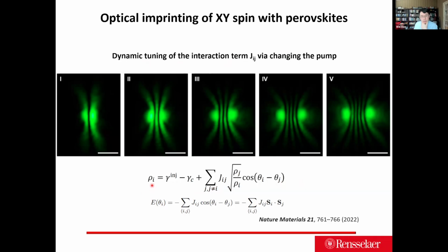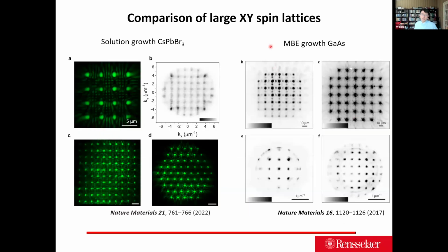So each spot density follows a relationship like that. So essentially one can map the system into a spin Hamiltonian the same way as the gallium arsenide system. So we can nicely, directly optically read the spin configuration in the two condensate case. And interestingly, we also want to compare the simulation in the large XY spin Hamiltonian. Here we optically imprint 4x4 lattices. And if you compare with the gallium arsenide in the real space, we can see an almost comparable result.